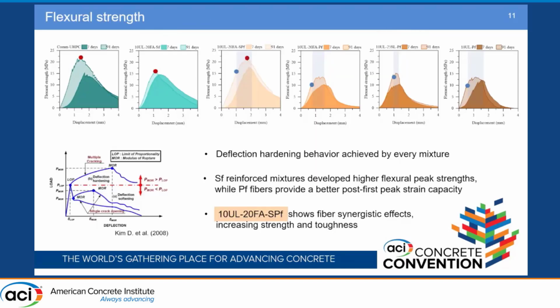We tested also flexural strength with a classic 4-point flexural test. When you test fiber reinforced concrete, you really want to get some toughness and have that kind of deflection hardening behavior. And that was the case for all of the mixtures that we developed and the commercial HPC. We saw that mixtures with steel fiber really showed a high peak strength, while polyethylene fibers really helped in providing a better first peak strain capacity.